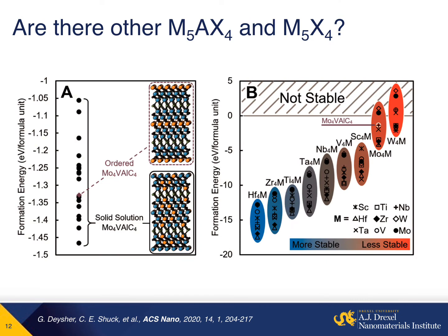After we discovered the first M5AX4 and the M5X4 MXene, a question quickly arose. Is this a unique structure, or is it a member of a larger family of MAX and MXene? We reached out to our computational collaborators at UPenn, and they did a high throughput study to understand what other M elements would be appropriate to make these M5X4 MXenes. And it looks like many MAX phases and MXenes could exist with a wide variety of chemistries. It seems that there's many different stable phases that can occur, and it's just an application space that hasn't been truly investigated yet. It may be the case that some of these require unique synthesis approaches, so using different oxides like we did for an aluminothermic reduction, or it could be that they just require very specific conditions to exist.